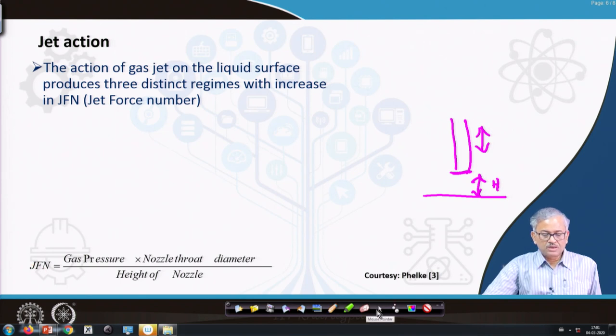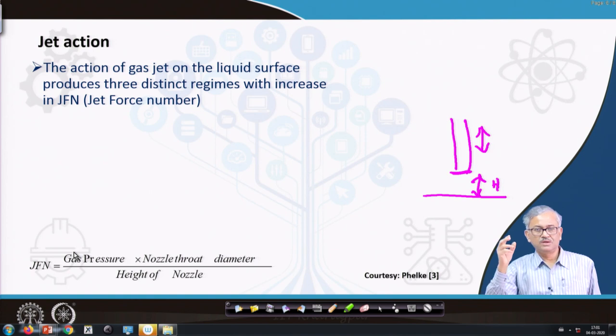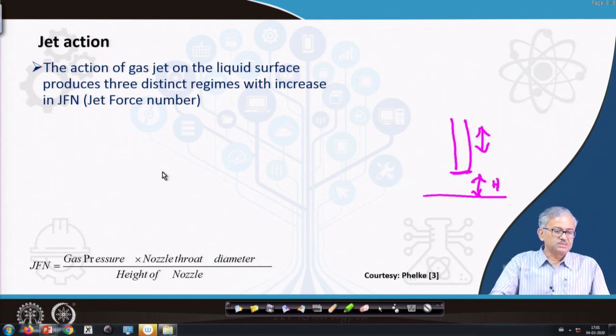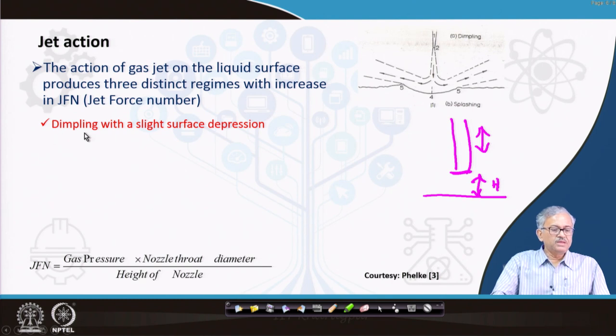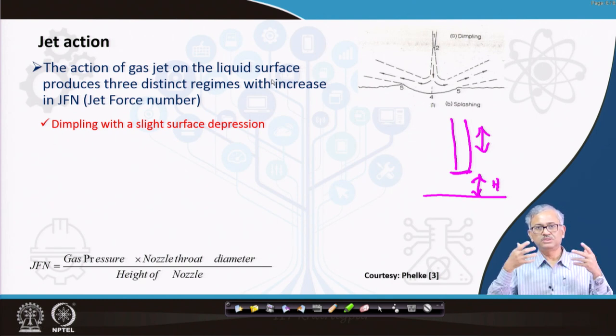When H decreases, JFN increases, that is, the jet force number increases and it makes more impact on the bath, right? That is the way the JFN comes into the picture. Now, there are three regimes, because depending on the jet force number you can produce three regimes.